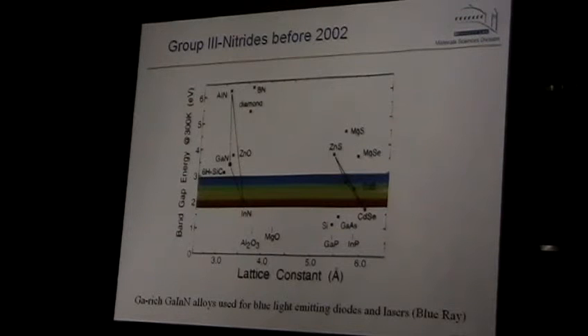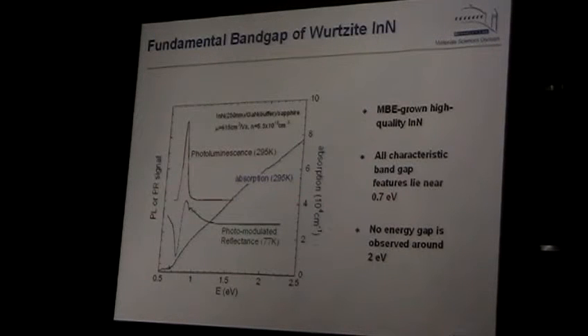But basically, this is a very successful material. However, if people were adding indium nitride, they found it's very difficult to make good material. Something was wrong. So we did research several years ago on this material, and we discovered that people for about 25 years were completely wrong. In fact, the gap is much lower. Band gap is only 0.7 electron volts instead of around 2 electron volts, which was assumed. And I will explain why people were so confused for so long.